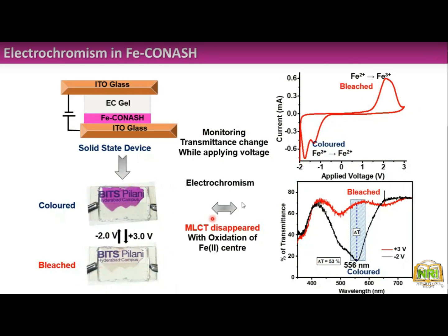Okay, and when we kept the whole device in the UV chamber, we can see again at -2 voltage or at normal condition, the spectrum here: transmittance is very less and lambda max is almost 556 nanometer, which is the color state. When we are applying plus 3 voltage, it becomes colorless. You can see here also this particular wavelength has decreased, the intensity has decreased, and this particular lambda max has almost gone. So it's bleached, and the absorbance has just disappeared. So this is how we are doing the electrochromism study.